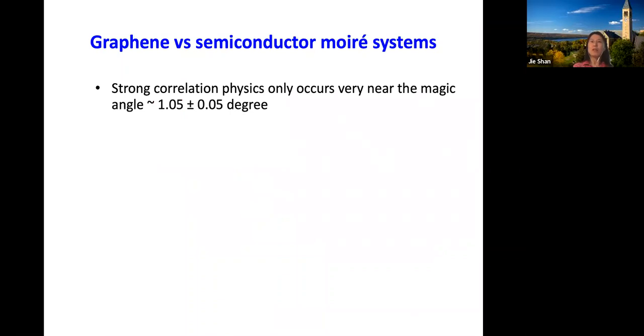So the graphene system is very magic. The strong correlation physics occurs near or very near the magic angle, that's about 1 degree. And that makes every device have its own personality. So if the angle is a little bit different, you may see somewhat different phenomena. That's interesting from some aspects, but also sort of annoying from a reproducibility point of view.